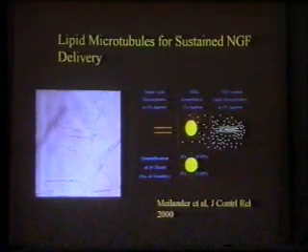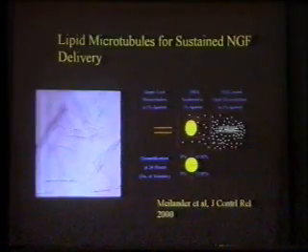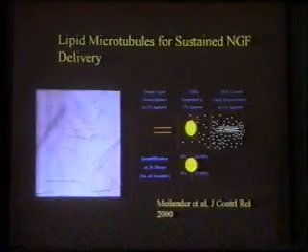And you have a slow-release system because by Fick's law, you just have diffusion coming out only from the ends of the tube when you have all this solution in the middle. So you can use this system to do slow release of proteins for about 4 to 6 weeks without a problem. And we've actually published at least 2 papers on this. This is one of them.